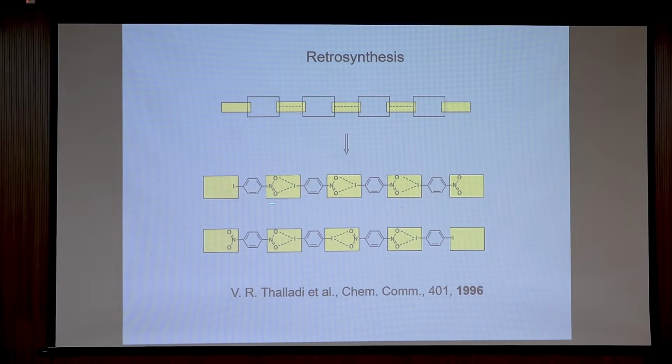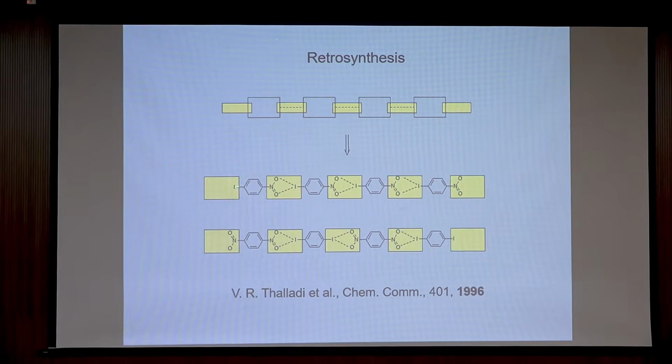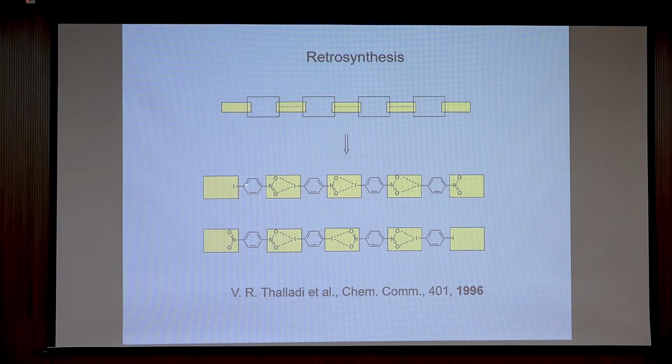So see, this is one of the synthons, iodo-nitro. So you can see para-iodo-nitrobenzene forms this nitro synthon. But you can get the same structure by taking para-dinitrobenzene and para-diiodobenzene. So a one molecule crystal has the same crystal structure as a two molecule crystal. So different molecules can have the same structure. See, already I am going away from that old style.